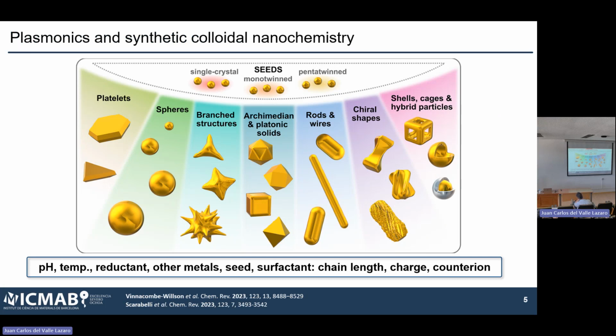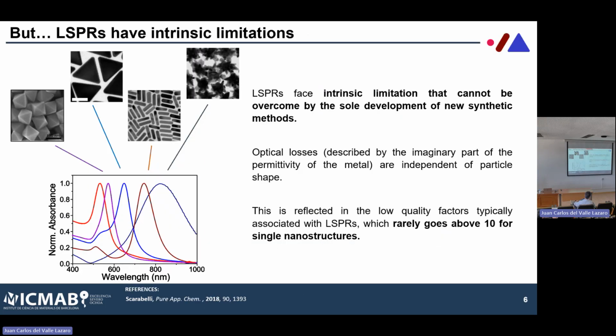So now we really reached the point where, by changing the parameters that we use for the growth of this particle, we can really finely tune how big they are, the composition, the shape, and so on. And so we got very, very good at this, at least for gold, silver, and the main metals. There's still a lot of work to do for other compositions. But again, my life as a PhD student was alive.